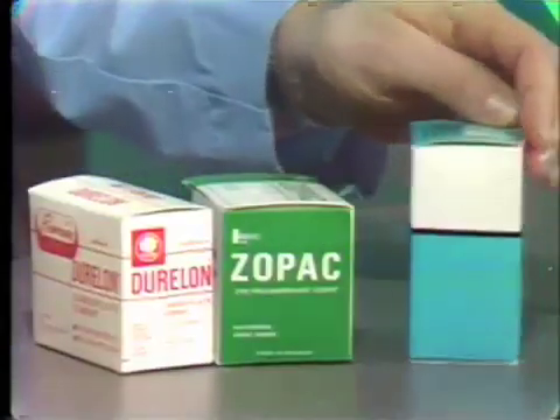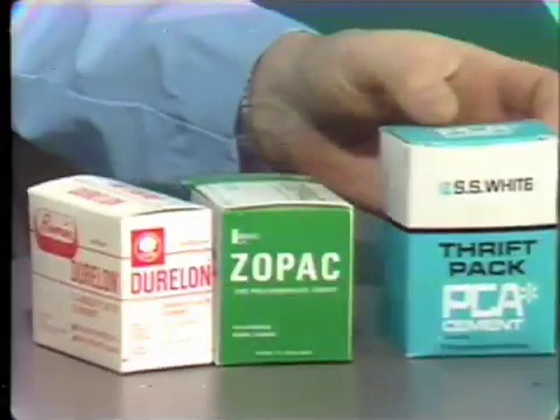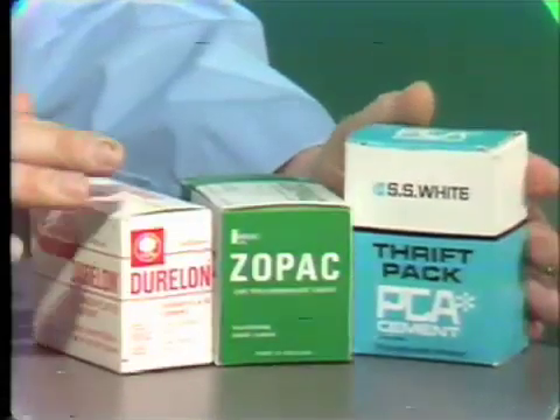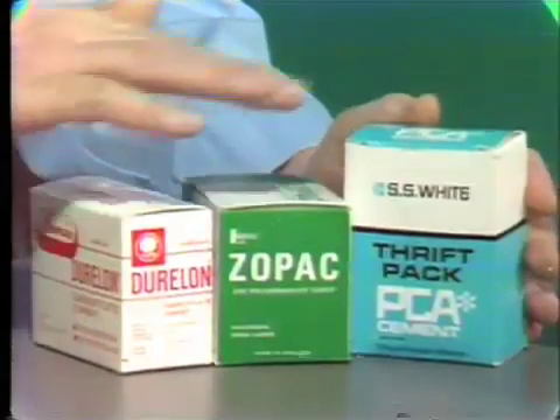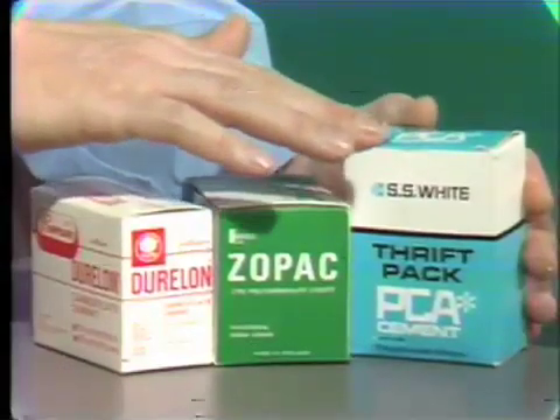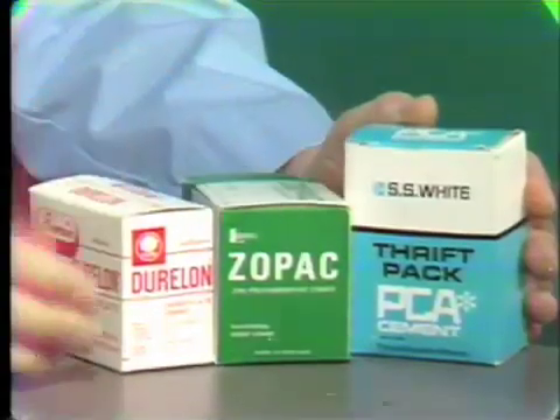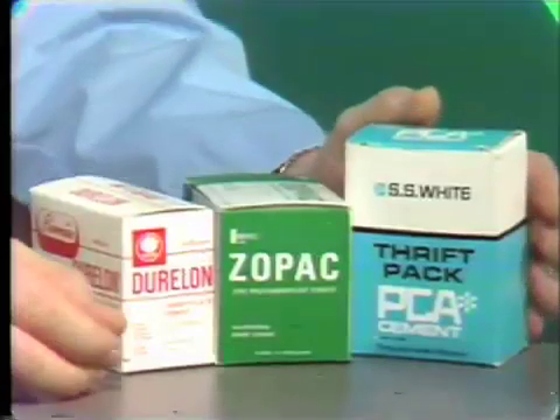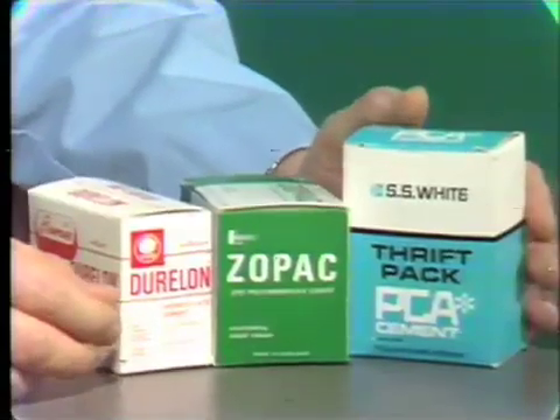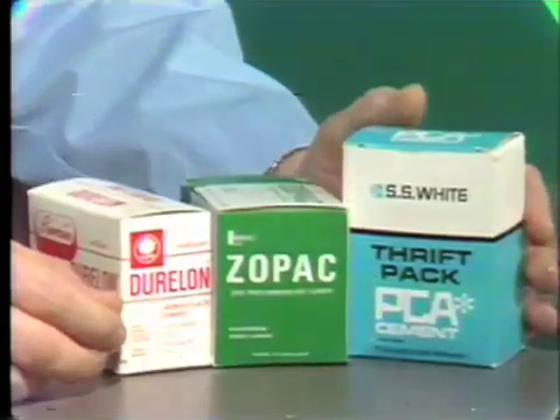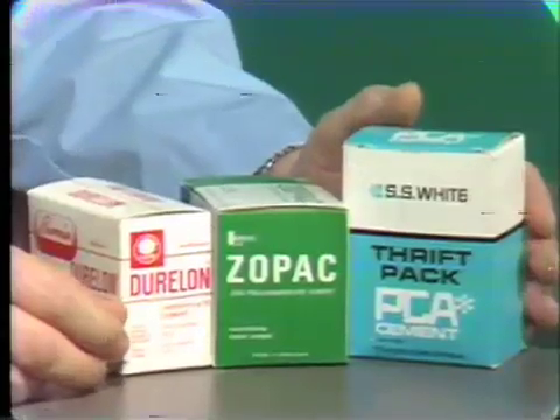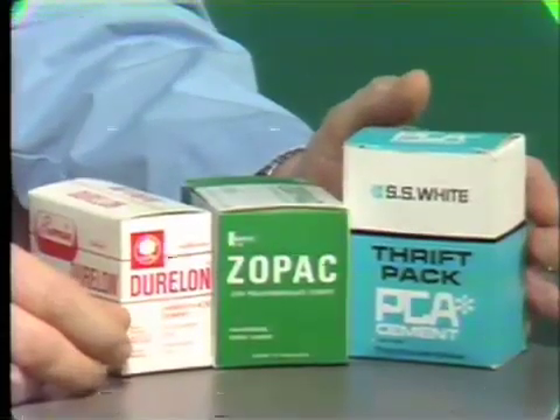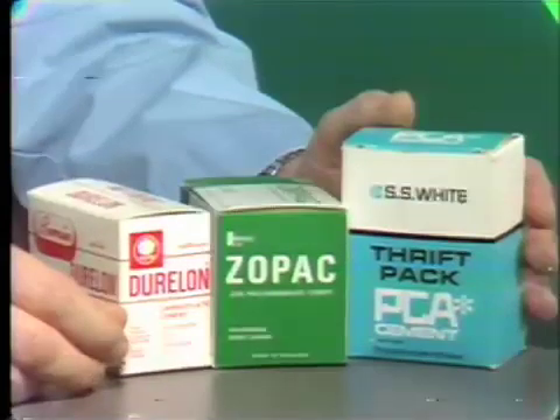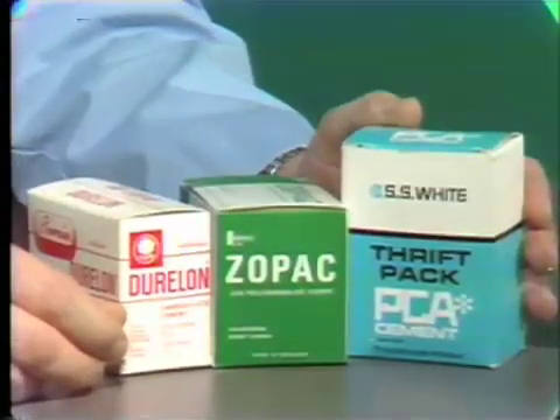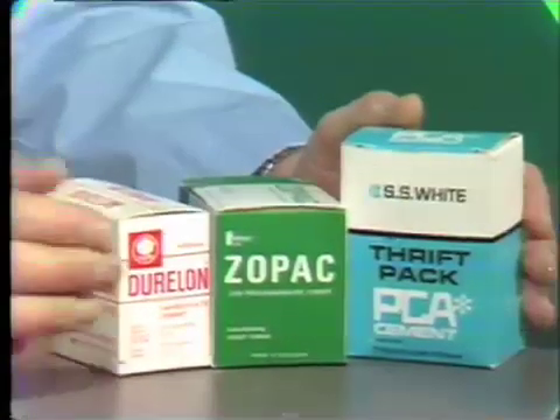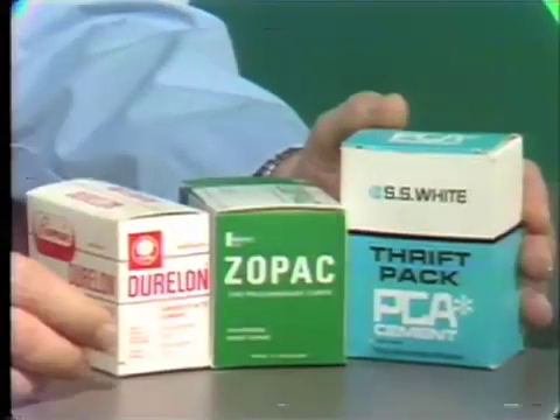The polycarboxylates have a little shorter working time than the zinc phosphate cements. The Durelon is around 2 to 3 minutes. The PCA cement may be as long as 5 minutes as far as the working time. They are strong. They have a strength of between 10 and 11,000 pounds. However, there is some evidence that there is some adhesion to the enamel, around 500 pounds, and maybe to dentin, 50 to 100 pounds. This is rather insignificant as far as the overall strength is concerned.